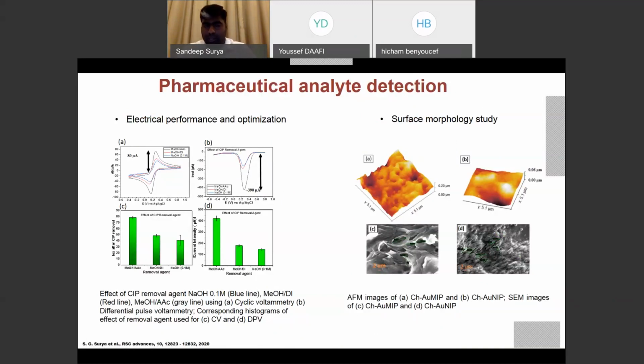Before going into the details, initially what I would like to show you is how we carried out the process of elution. In the process of elution, we tried with three different kind of solvents, one being methanol with acetic acid in certain ratio, and methanol with DI water and sodium hydroxide. Among the three, what we have figured out through cyclic voltammetry that I've shown here in the figure A, and through the DPV, these are the measurements that we did after the process of elution. So from there, we identified that the highest current has been recorded for methanol and acetic acid combination, which essentially says the more number of ciprofloxacin has been removed from the MIP adduct, giving us the MIP.